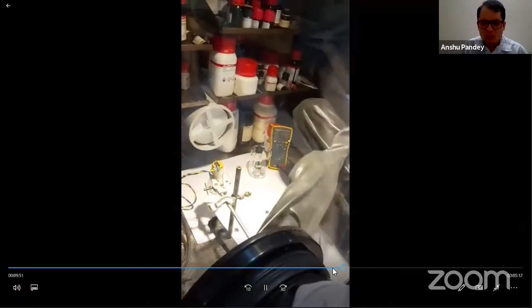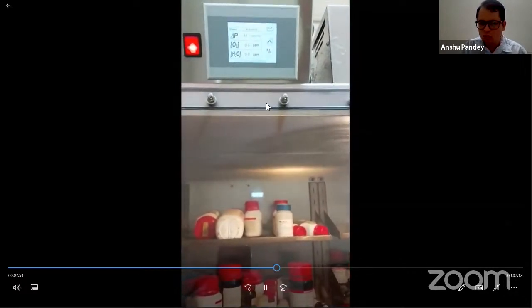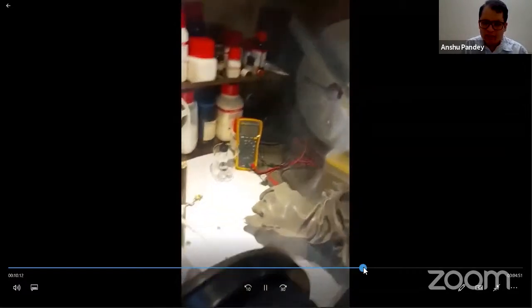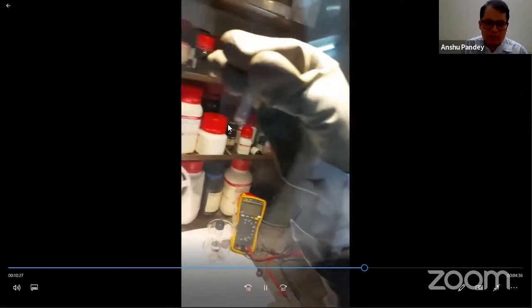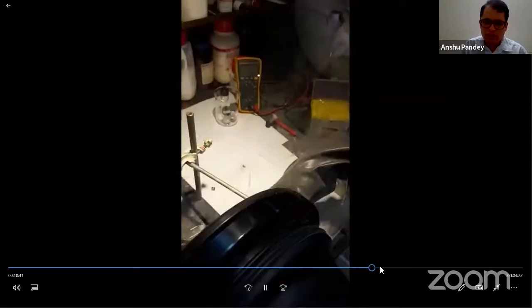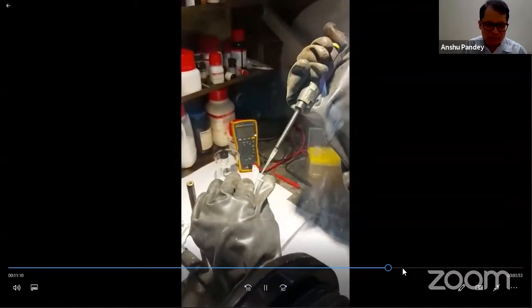There is nothing really interesting happening. It just looks like any other sample of gold silver. In fact, it would look like a very poor sample of gold silver. So if we move on now, this solid which we obtained from centrifugation is moved into a glove box. The glove box, as I've tried to show, I guess at some point, is kept around 1 ppm. So what is done is these are moved in, these have been dried, and now these are being redispersed into chloroform, which is now used for the casting. So these are cast out of chloroform, and subsequent to the casting, this is what is happening here.